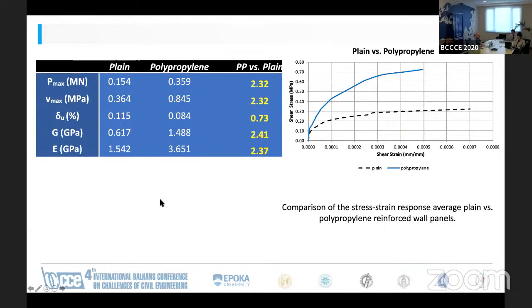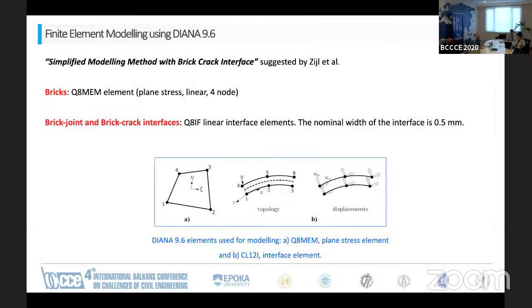Regarding ductility, this is an interesting case, because we added a very stiff mortar at a ratio of 1:1, the wall didn't have large ductility. So it had less than the unreinforced panel. However, if we compare the shear strength, it is considerably high. For this reason, in the future tests, we had to change the mixture and the composition not to be 1:1, but 1:4.